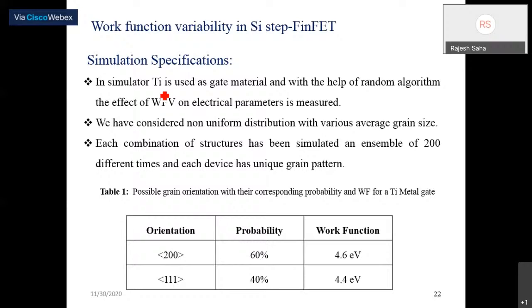In order to study this, we have considered titanium as the gate material, and we have used a random algorithm to study the work function. WFV means work function variability, whose effect on electrical parameters is measured. We have used the random algorithm in the simulator to study the effect of work function variability in the step FinFET structure. Also, we know that the metal has some grains, and we have considered non-uniform grains with average grain size. We have considered various grain sizes, and for each combination of the structure we have simulated 200 times to find the variation in electrical parameters like threshold voltage, on current, or subthreshold swing, etc.